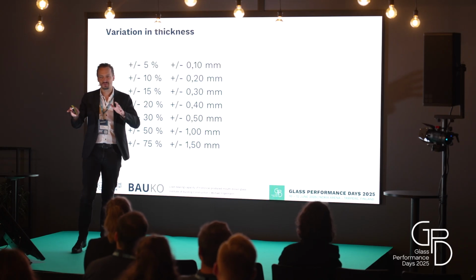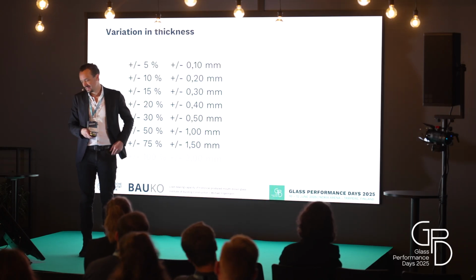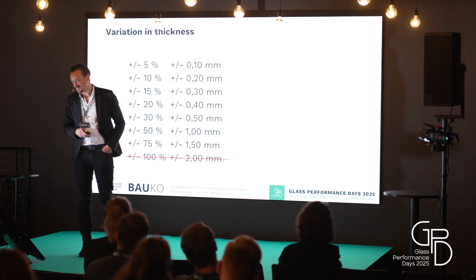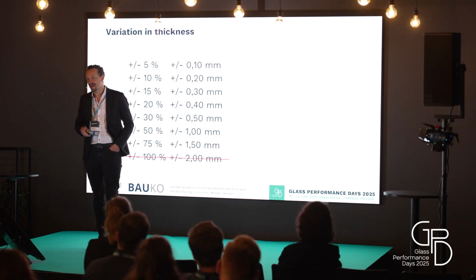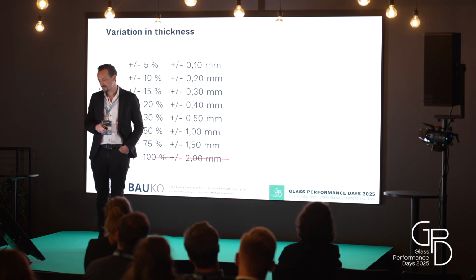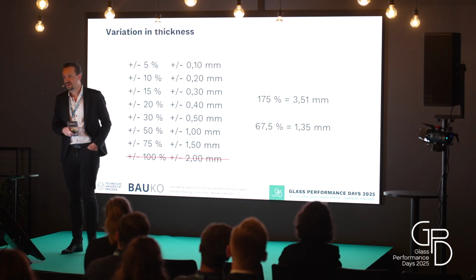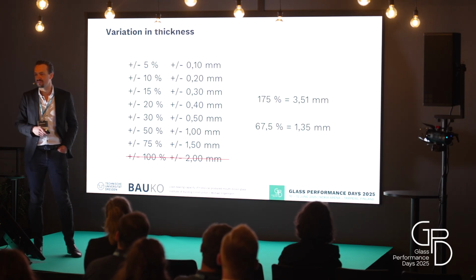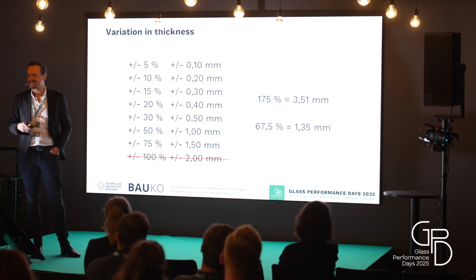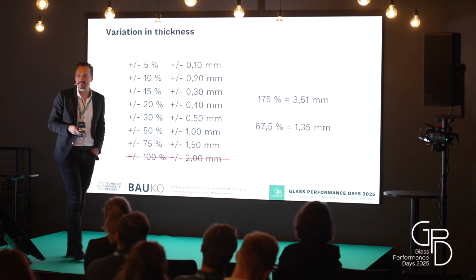Okay, so you get an indication, right, of what your feeling is of what you find. Plus minus 100%, of course, doesn't make sense, so I cancel this out. What you actually measured for 2 millimeter thick glass was a variation between 3.5 millimeters and 1.35 millimeters. So I think this is quite excessive, especially when you recognize the values you see with float glass.